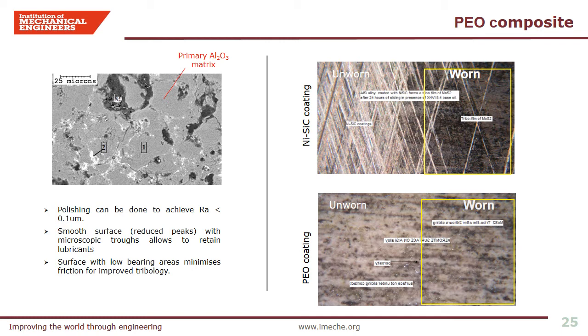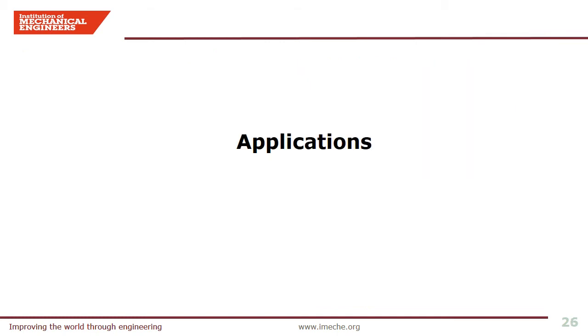This slide shows how porosities in the PEO coating can be beneficial features, not only to offer flexibility and low stiffness, but also act as reservoirs for impregnation and retention of lubricants, thus giving the surface a composite nature offering low friction and low wear. Hard coatings such as nickel and silicon carbide are often crosshatch honed to retain lubricants, but these grooves disappear fairly rapidly during wear, minimising the lubricant film and displacing it from contact zones. PEO coatings with a pore reservoir filled with lubricants offer better retention of lubricants and subsequent surface durability. On the next slide, we will discuss some interesting projects including space and automotive applications.